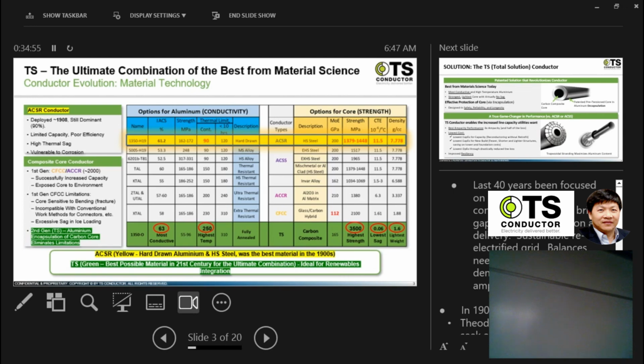And to address that issue in terms of heavy core and highly thermally sagging core, I'm going to skip EMR here because we don't use EMRs in the US. The EMR story here, they have a very low thermal expansion, but they have very lousy strength, so they had to combine with one of these high temperature aluminum alloys, which makes them very lossy. And they also are magnetic in terms of steel properties. So what it means is they've got a huge surge impedance. They cannot go very far, and you have to use a lot of capacitors to compensate for the inductive impedance. And by the way, invars are very expensive if you do have to consider invar.